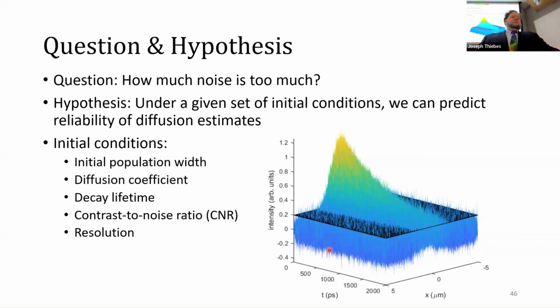This axis here is time. Back here at time 0, you have this tall peak. And then as time goes on, it spreads out and diminishes. It's undergoing both diffusion and decay, and both of those things are decreasing the actual height of the peak. Over time it drops down, and this black plane is something I put in there artificially to represent what we learned in instrumental analysis, the limit of quantitation, so to speak. As it drops down, we can see more and more of the peak dipping below the level of quantitation.